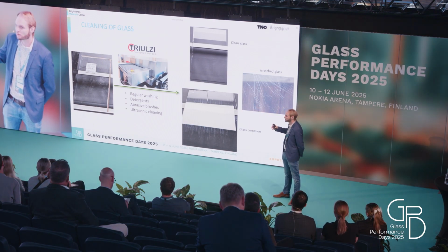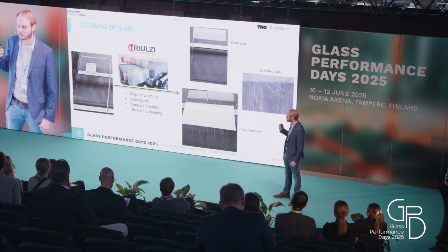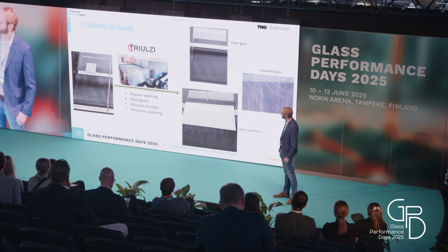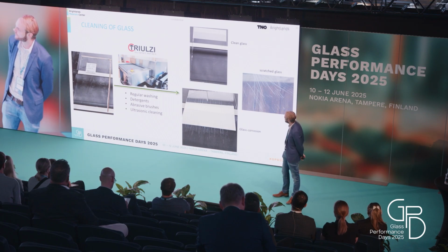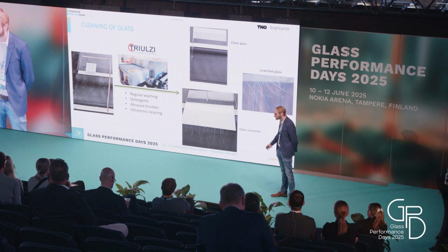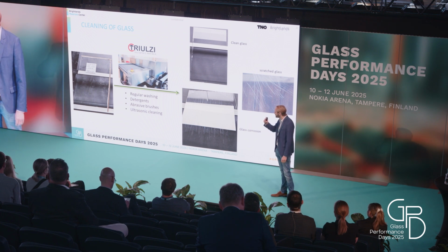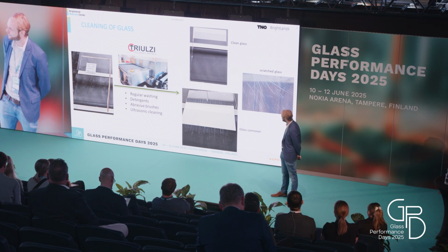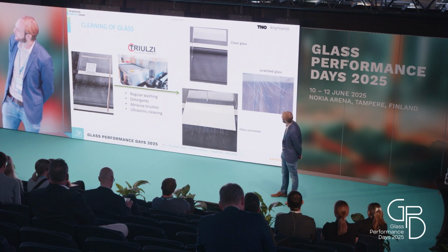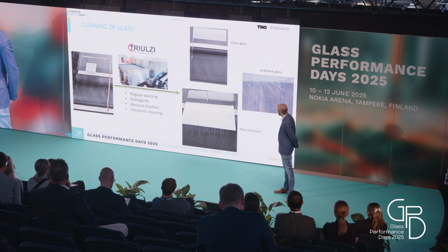But in an industrial process, you would like to use as much of the glass as possible. So actually, you don't want to do the edge trimming. And this is also one of the strategies where we're developing together with Triulzi to see how you can properly polish the edges to remove the sealant, and in an optimized scenario, then get clean glass out of it.